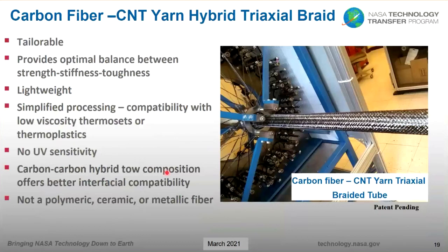After braiding, the braiding parameters were established with the carbon fiber only control. I then loaded the braider with the hybrid tows, and we developed the hybrid tube that was shown in this image. During braiding, these bobbins actually rotate in a figure-8 direction. So basically, these fibers are moving over and around one another as it is being braided onto the mandrel.